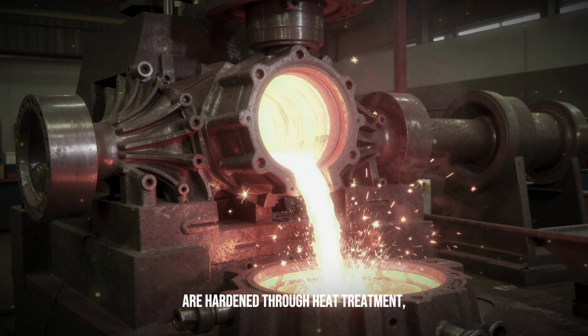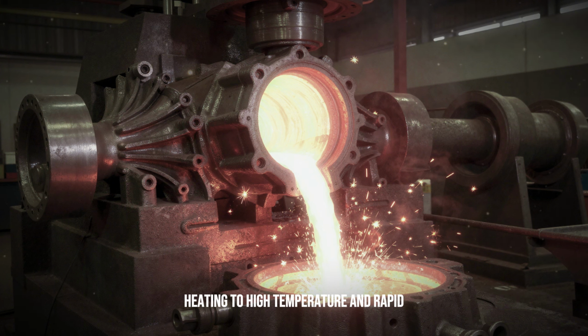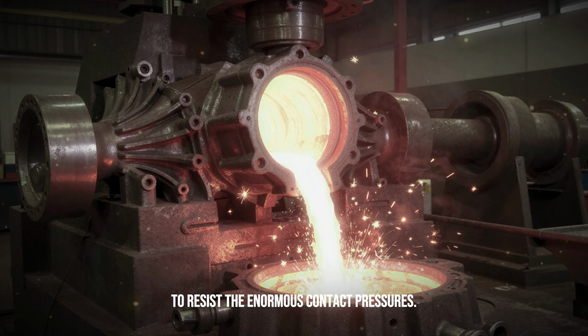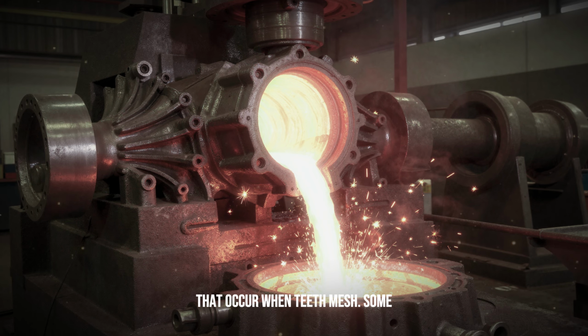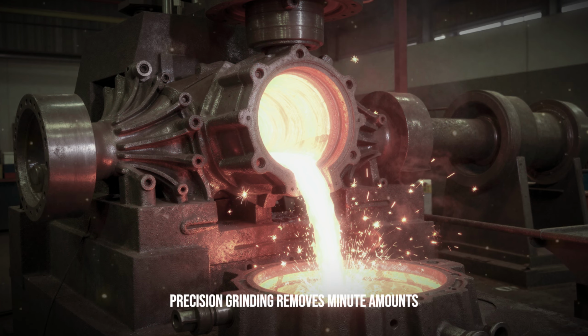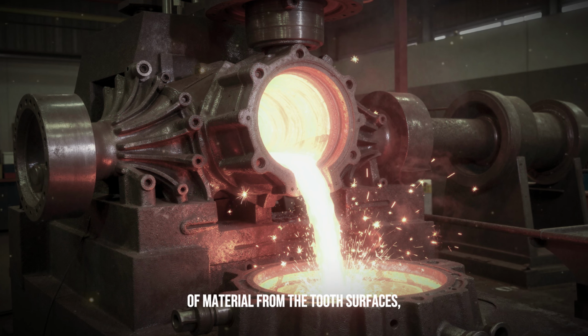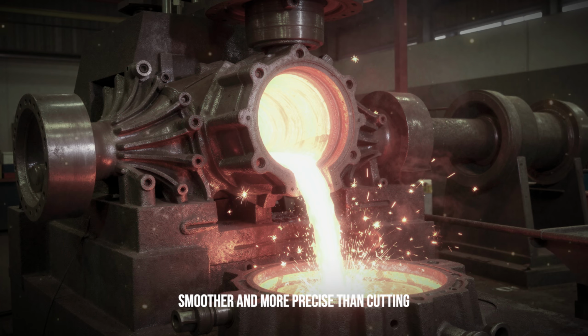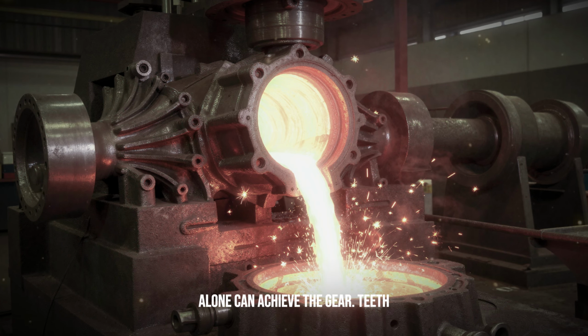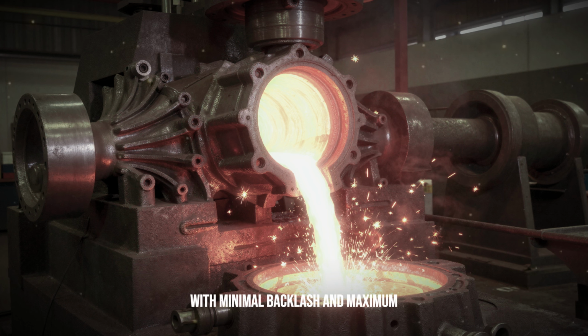After cutting, the gears are hardened through heat treatment, heating to high temperature and rapid cooling, to develop the hardness necessary to resist the enormous contact pressures that occur when teeth mesh. Some gears are ground after hardening to achieve even higher precision. This precision grinding removes minute amounts of material from the tooth surfaces, creating a surface finish that is smoother and more precise than cutting alone can achieve. The geared teeth are now ready to mesh together with minimal backlash and maximum efficiency.